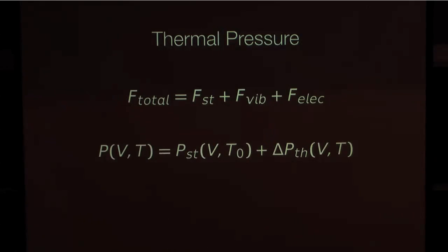Yes, also in the case of solid solutions, you have a term of configurational free energy coming from the configurational entropy. Right. So the equation of state that I'm describing here is valid for fixed composition without phase transformation. It's a relation that describes the pressure, volume, and temperature in the stability field of one mineral at fixed composition. That's what I'm aiming at here. Yes, but even with a fixed composition, you can have several sites, order-disorder. Yes, then you need an additional term. Yeah. Thank you.